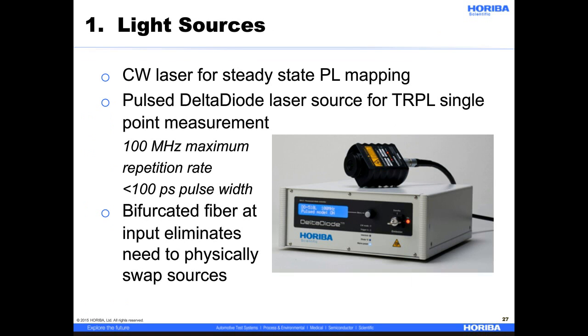For the light sources, a CW laser was used for steady-state PL single-point and mapping measurements. A pulsed Delta Diode laser source was used for single-point, time-resolved photoluminescence measurements. The Delta Diode source has a maximum repetition rate of 100 MHz and a pulse width of less than 100 picoseconds. A wide variety of Delta Diode sources are available, ranging from the UV to near IR. A bifurcated fiber was used to couple both sources to the microscope head, eliminating the need to physically swap sources when changing experiments.